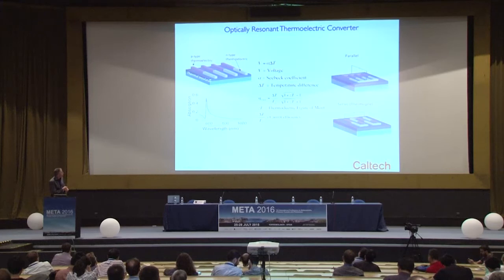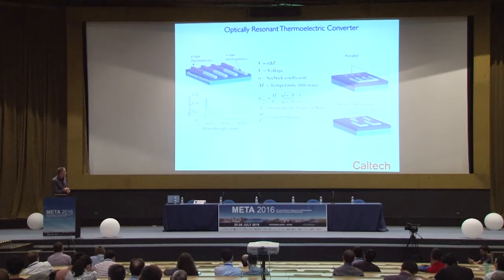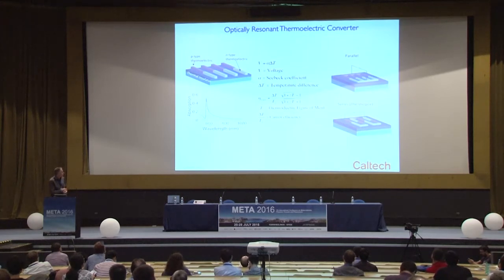And these bismuth antimony telluride materials have the interesting property not only of being topological insulators, but also of being very efficient thermoelectric materials. And so by making an array of resonantly excited thermoelectric nanowires, we form an array of so-called guided mode resonant structures, where a periodic array of nanowires couples to a dielectric waveguide mode. It's possible to achieve extremely narrowband resonances and resonantly absorb the incident optical energy very efficiently in a very low heat capacity environment of a freestanding membrane with thermoelectric nanowires, either wired in parallel or to build voltage in a series thermopile configuration.